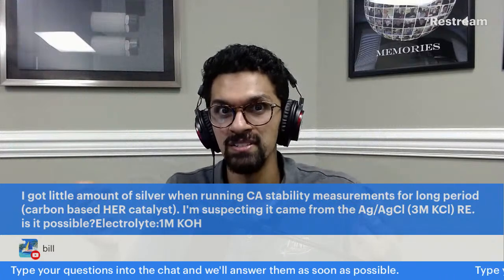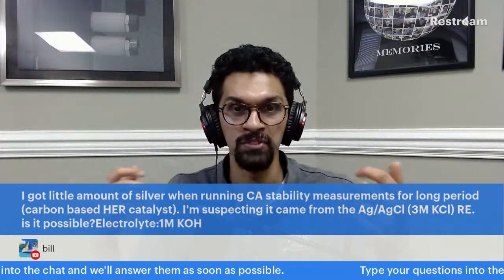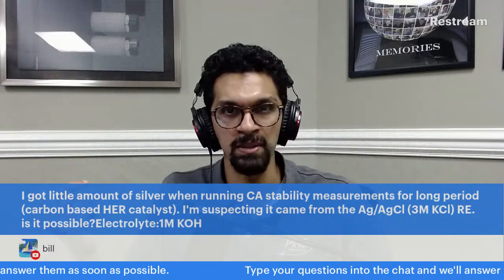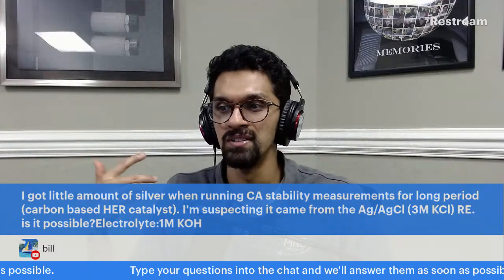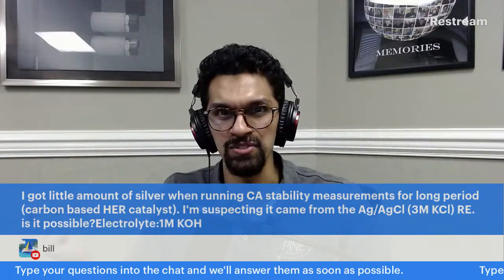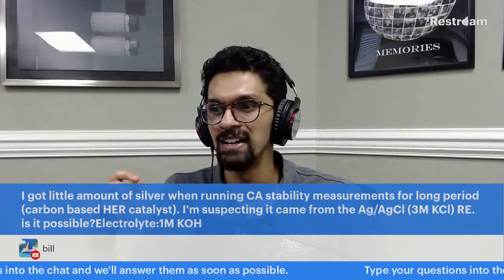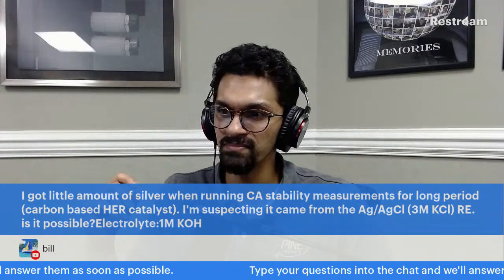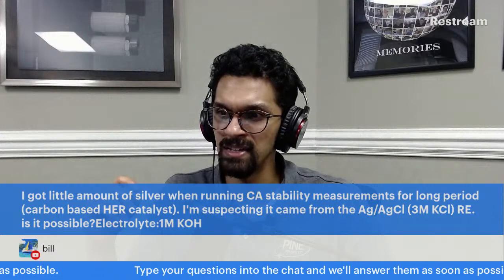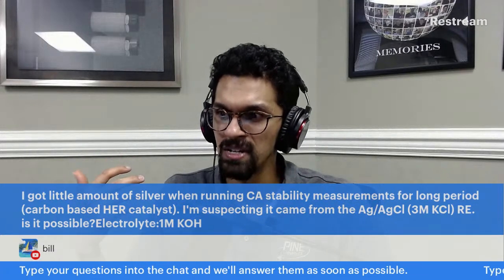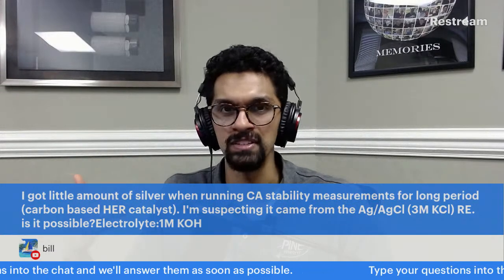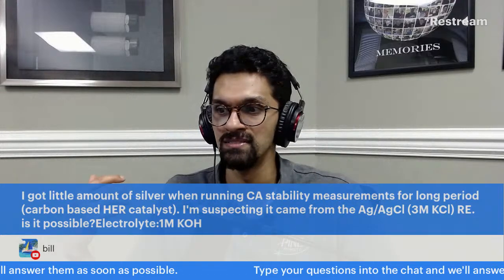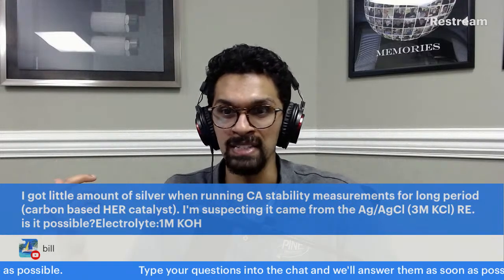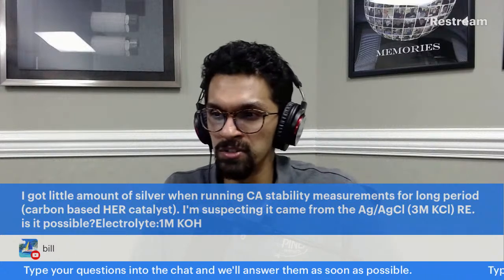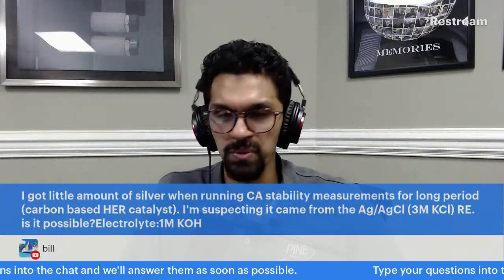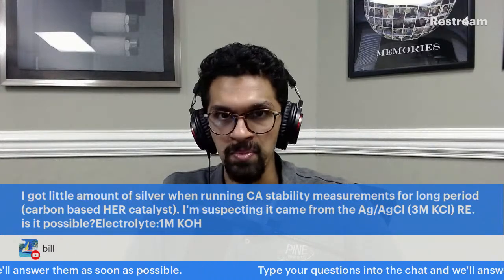Not because of the silver, but because 1 molar KOH is really at the cusp of, it's alkaline, so it can etch glass. If you had a dilute alkaline solution, you might be able to get away with some of these experiments. But as you move to 1 molar and even higher concentrations, you'll start to etch away the glass. And yeah, I think this just sounds like a contamination issue. But because you have these different electrolytes and the KOH is in some way reacting, I do believe that you may be getting some silver when running a long chronoamperometry experiment.